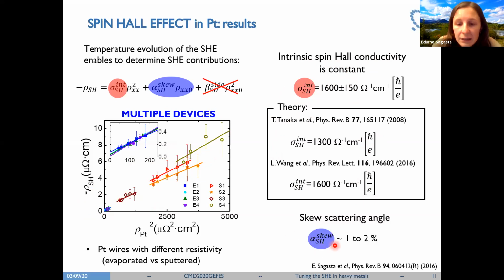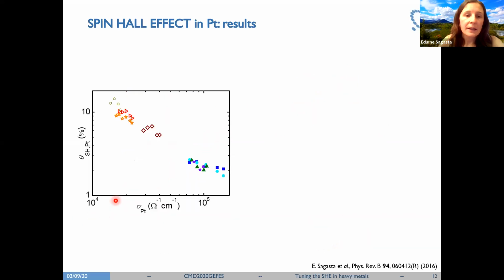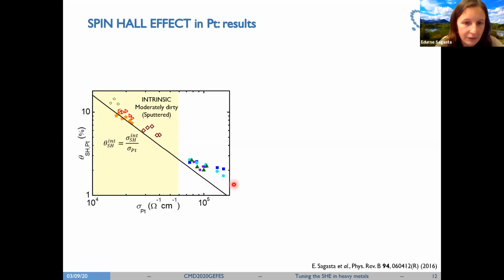Regarding the skew scattering angle, we see that it changes from 1 to 2% and is slightly different for the sputtered and for the evaporated data. Now, here we can see the spin Hall angle value that we obtain as a function of the platinum conductivity. If I plot here only the intrinsic contribution, this is the black solid line, we see that the sputtered data nearly merge into this black solid line. However, to explain the high conductivity data, we need to also consider the skew scattering contribution. Note that we are in the logarithmic scale.